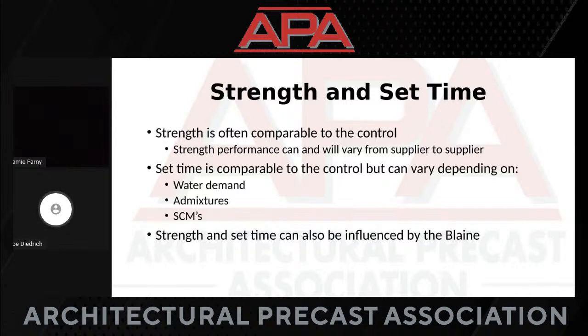So, because in architectural precast you are looking at oftentimes similar color, maybe a little bit brighter. Strength and set time. Again, its strength is comparable to the control, PLC versus an ordinary Portland cement. A cement supplier typically is going to try and produce a cement that you can pull one cement out and put the other cement in and have similar performance. Part of that performance includes set time. Set time can vary depending on water demand, admixtures, SCMs. Those three, water demand, admixture, SCM, go hand in hand. That will influence your set time. If your water demand's up, your set time is going to increase.